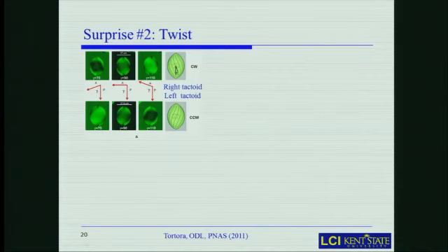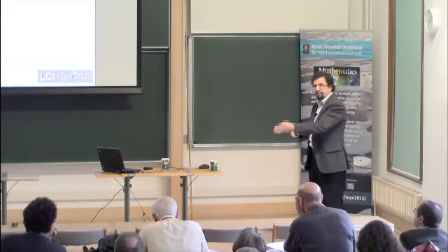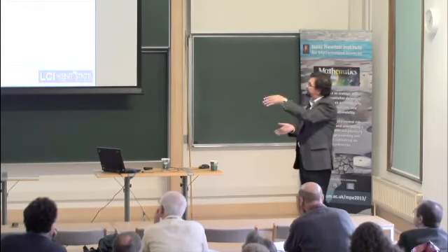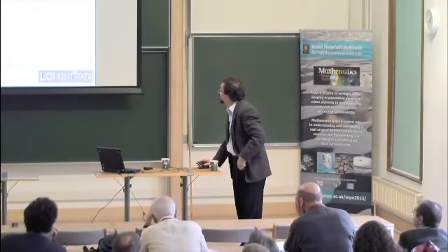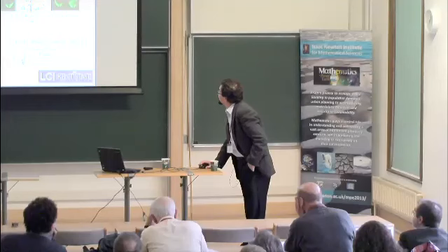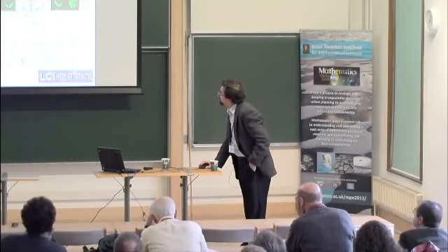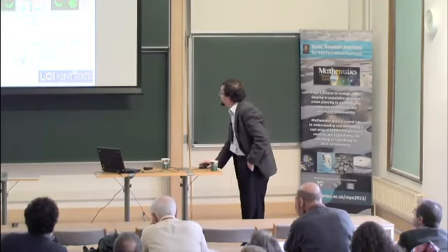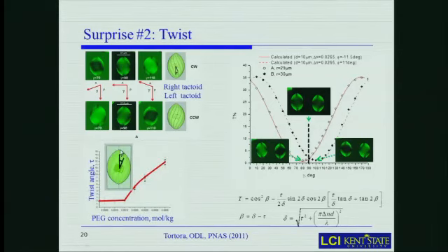To those who know a little bit about propagation of polarized light, it means that the polarization plane of light has been turned either to the left or to the right, and we can establish this by observing the tactoids with differently crossed polarizer and analyzer. And what we realize is that the tactoids are in fact twisted. Half of them twist the director to the right, half of them twist the director to the left.